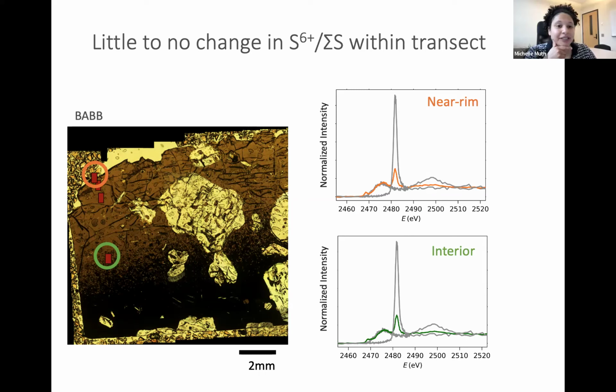It is a feature that's sometimes observed in glass and sometimes not. There's a little bit of debate as to what specifically it's associated with in terms of glass chemistry, but everyone agrees that it's due to iron sulfur complexing. Most people's opinion is that it's related to iron sulfur complexes in the melt structure. There's some people that have argued too that it could be due to micro sulfides that are undetectable, which is hard to test, but we don't see much difference in terms of our ability to extract information about sulfur valence state based on whether or not it's present.